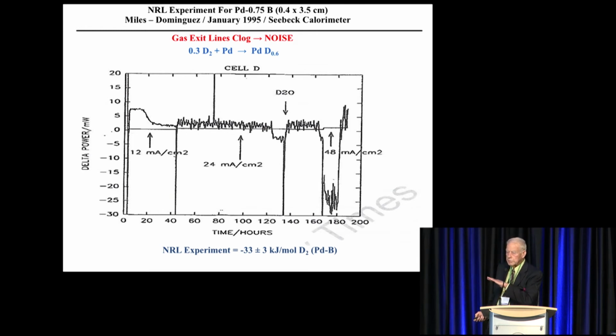Well, the gas exit lines are carrying water vapor, heavy water vapor. If they're horizontal, that's going to condense at lower temperature, at room temperature, and so they get clogged. They don't clog right away, but as you go on, they get clogged, and then pressure builds up and is released, and builds up and is released, and so you get this noise. But it lasted for 40 hours, enough to see the effect of loading. And this even stayed higher than it really should be right here.